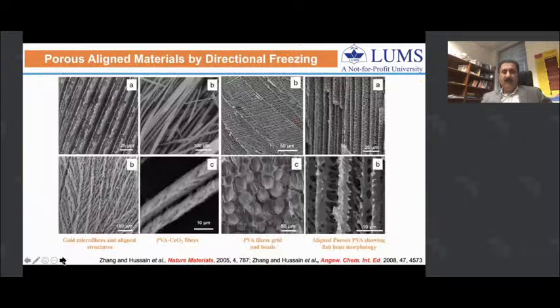Lastly, we also developed this very simple directional freezing approach by which you can use a concentrated dispersion of nanoparticles, could be metal oxide or even polymer nanoparticles. You freeze them directionally, and by freeze evaporation and freeze drying, you can make a variety of new materials depending on what material they were frozen in.